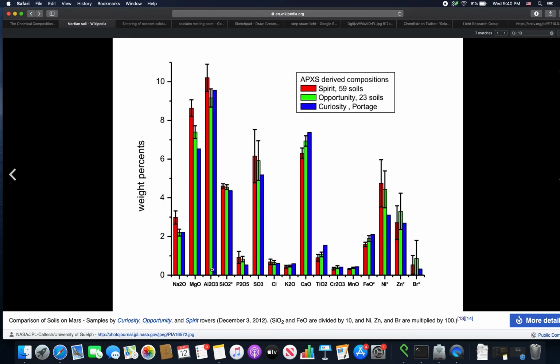Silicon oxide, magnesium oxide is also very similar to calcium oxide in those properties. So the majority of it would be fused easily and fuse the rest of the stuff together, at least for lunar stuff. There's also an effect going on that's a eutectic mixture, and a eutectic mixture would lower the melting point of everything even more and make stuff fuse more easily. And that's if you have all these complex chemicals together.